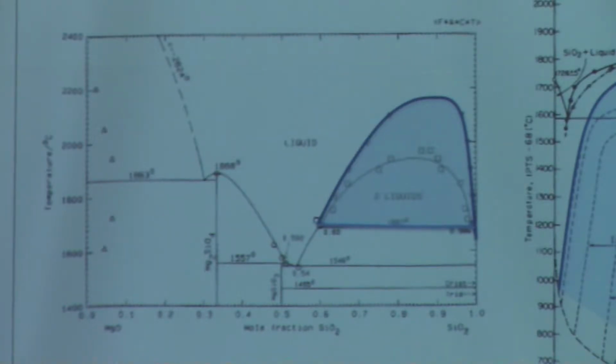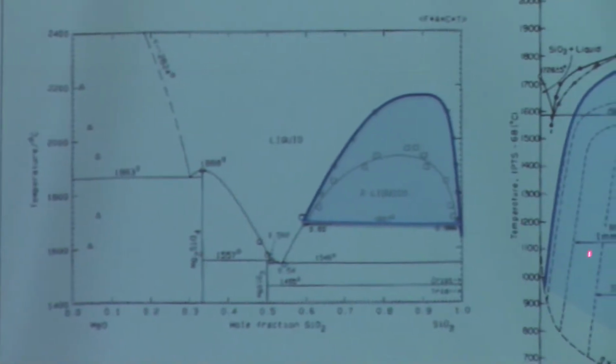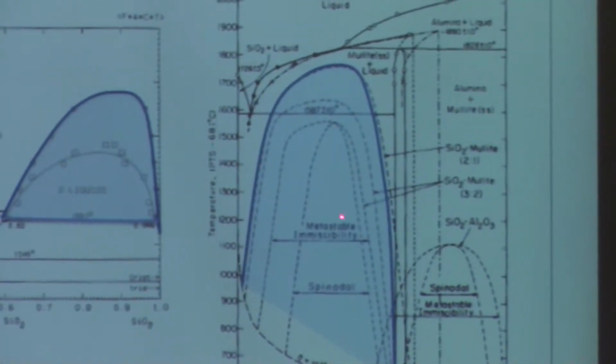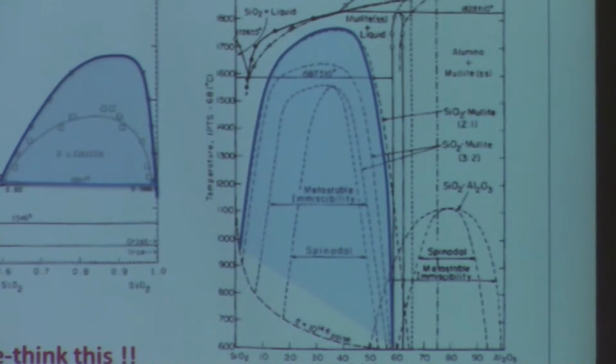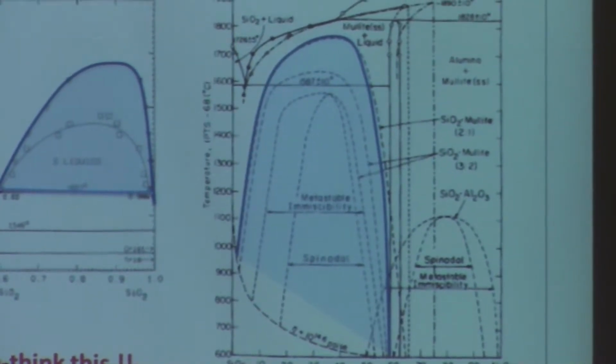However, you can't mix much alumina into silica without getting what's called a phase separation. Again, oil and water, because the structural elements of the silica and the alumina are different enough that they don't like to mix, not much. Okay? So you can't put much of this in here. And again, your periodic table just got smaller. So what do you do?